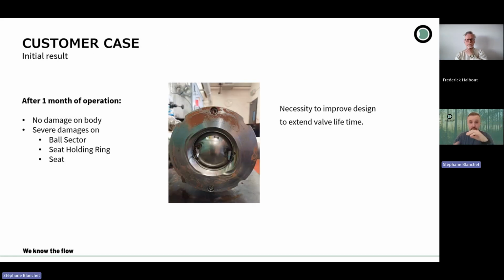All right, so that's what we provided a few years ago. This is the result after 1 month. The good thing is that the body was completely intact. That was the good thing. But you see after 1 month, some parts were completely damaged. So the ball sector, the seat holding ring, like the cover ring, and the seat. So that was obviously not good enough. And fortunately, we have a customer with which we have a very good communication, and together we tried to find a solution to improve its lifetime, to make sure that we can improve, of course, the lifetime and investment for this type of valve.